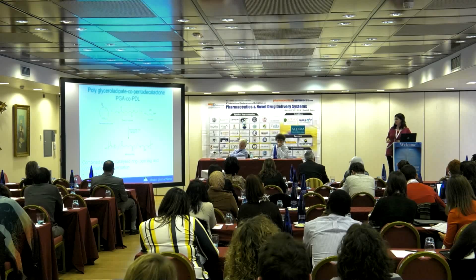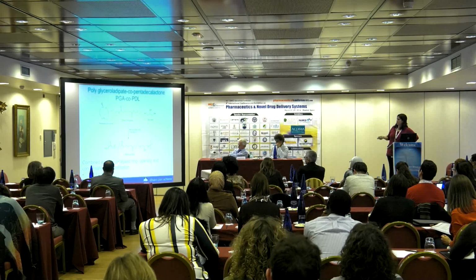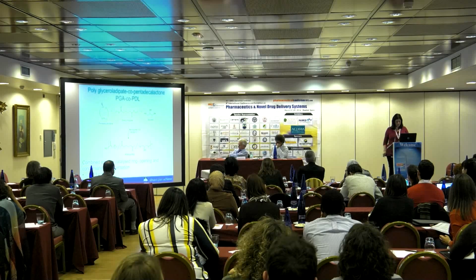Just now, we're also working a lot on using functionalized monomers based on these, which gives us a lot more opportunity to do click chemistry and add different linkages on there. We synthesize these enzymatically, and this allows us to retain the activity of the secondary hydroxyl group. So it's a linear polymer we're synthesizing. It's not a network. Typically, molecular weights are about 16 kilodaltons, which is really as much as we get with this system using enzymatic catalysis.